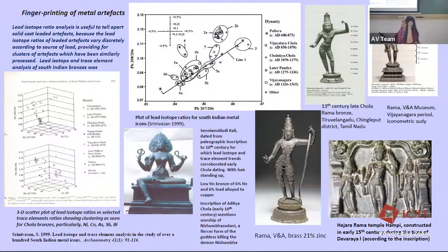So even without being able to pinpoint ore sources in a very decisive way, you still get some pretty useful information. And of course, the lead isotope ratio data was then put together with the trace element data. You find that some of the trace elements such as nickel, cobalt, arsenic and bismuth, even though they are traces, when we call something a trace element, we mean that the composition is less than 1%. But even with that less than 1% composition, there are some affinities with the copper source because they tend to be chalcophilic. So if there is some clustering that we see, then it is meaningful in the sense that it could represent different copper sources. And that's why you're seeing a certain clustering at a particular point in time, because they were using copper from particular sources. Based on these aspects, I was able to find a way to tell apart the metallurgical profile of the Chola bronzes from the Pallava bronzes to the Vijayanagara bronzes, and using that I could do some reassessments.